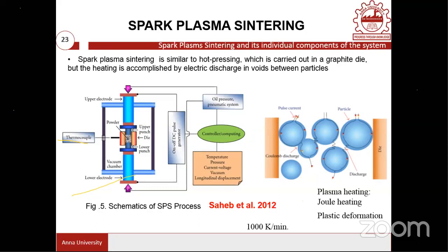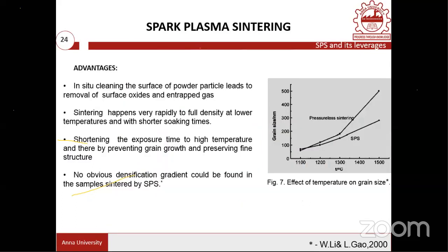And the heating rate would be really 1000 Kelvin per minute. Therefore, heating can be done at a faster rate, and cooling can also be done at a faster rate.